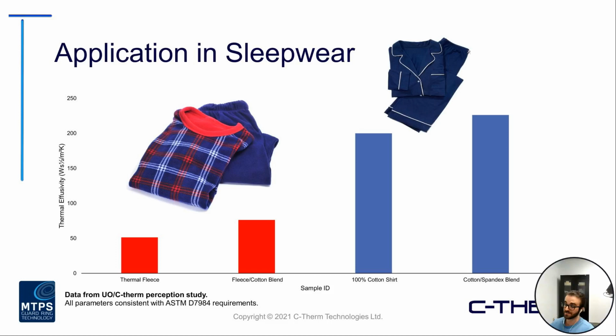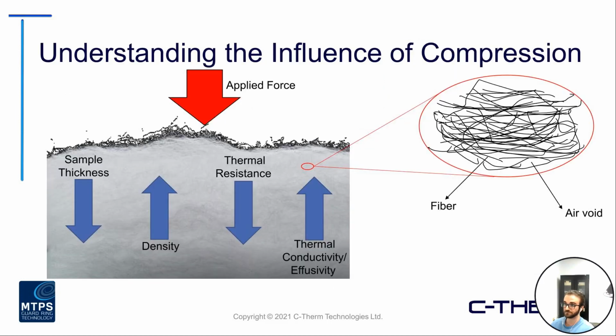The highest effusivity measurement that we're reporting here is the cotton with the spandex blend. And I will note the spandex component of that sample was very low, maybe about 1 or 2%, but compared to just a pure cotton, again, showing that net increase. So a few different examples of how you can use these effusivity values to fine tune and control the desired properties for your specific products.